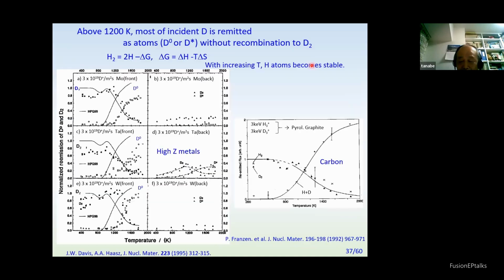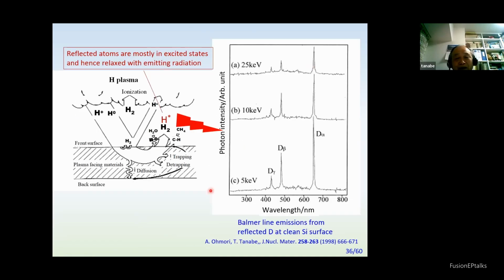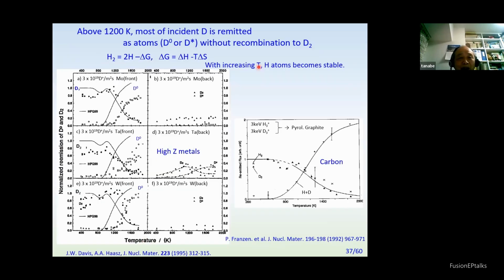So reflection is very important, and also at higher temperatures, re-emission occurs not as molecules but as atoms, because hydrogen dissociates this way. At higher temperatures, the reaction goes this way, so with increasing temperature H atoms become more stable, and the emission at high temperature comes to deuterium—this is the same for carbon.